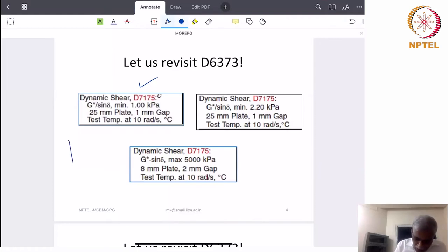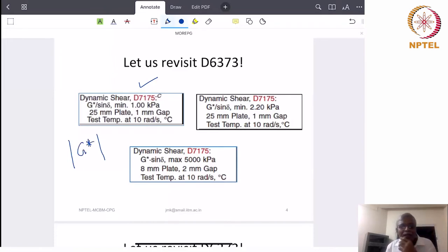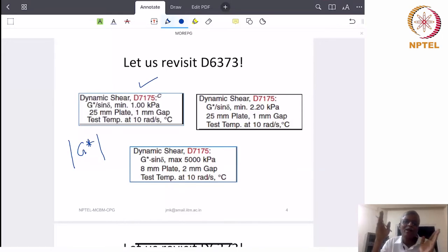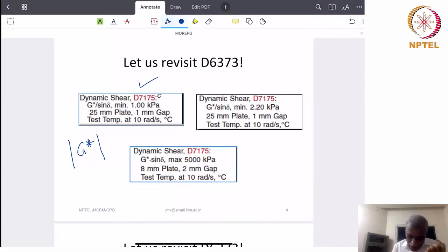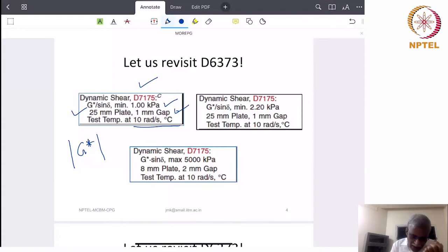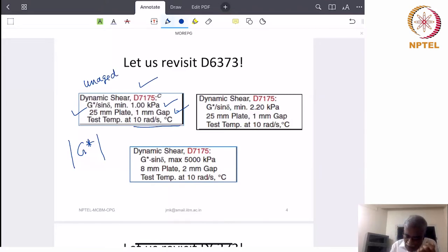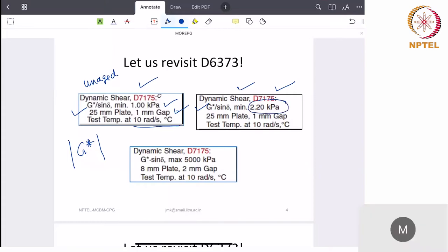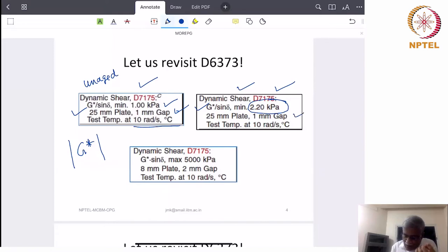Let me make this a little more clear. It is actually the dynamic modulus, what is normally called by practitioners as the complex shear modulus — you have to write it with two vertical bars. So G* by sin delta, minimum 1 kPa, using a 25 mm plate with 1 mm gap at 10 radians per second at the test temperature — this is for the unaged condition. For the short-term aged condition, it is the same dynamic shear rheometer D 7175, G* by sin delta, but here it is 2.2 kPa, 25 mm plate, 1 mm gap, at 10 radians per second.